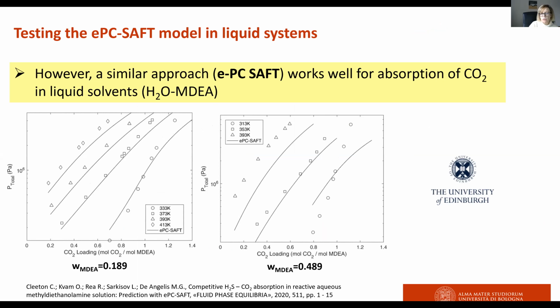Of course, the comparison between the model prediction and the data becomes worse in the case of solutions containing a higher amount of aminic component, which is of course more challenging for the model. But in the case of a lower amount of MDEA, we have a good prediction of the absorption curves by the model.